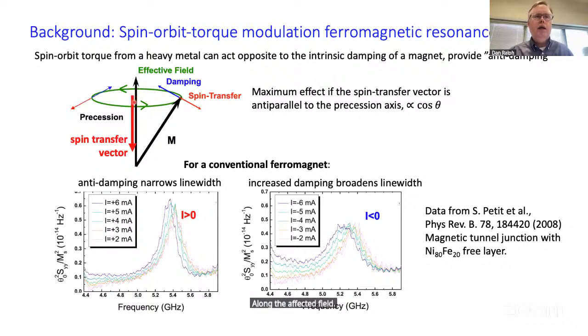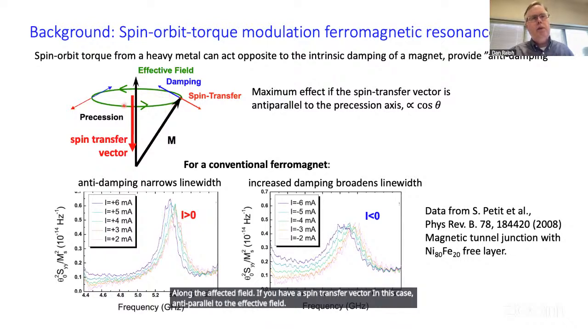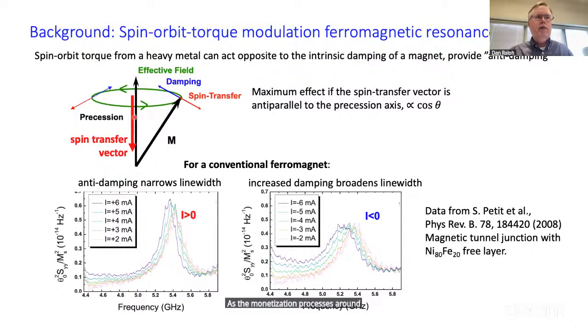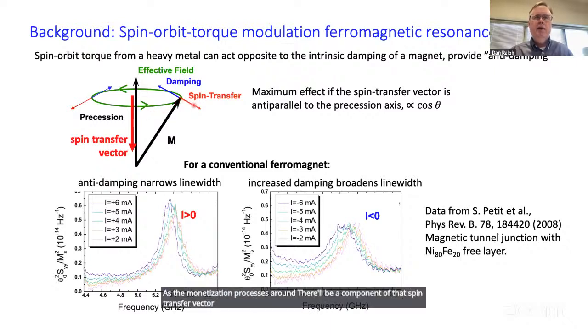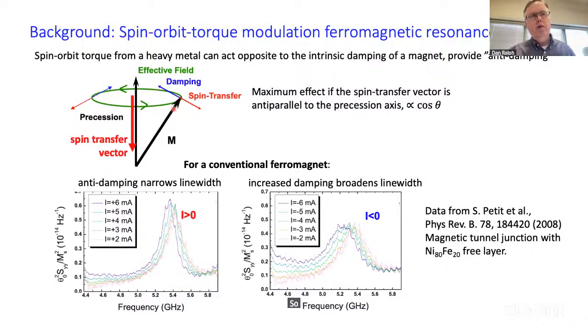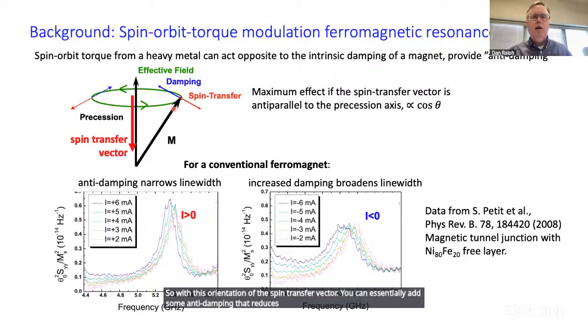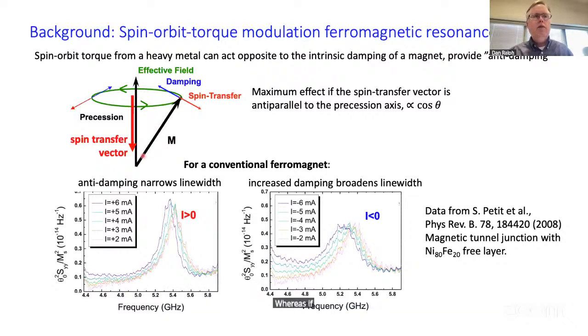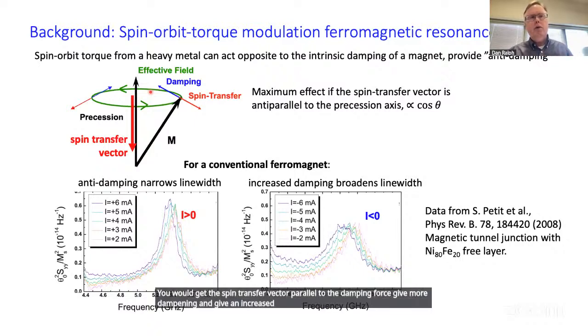If you have a spin transfer vector, in this case, anti-parallel to the effective field, as the magnetization precesses around, there'll be a component of that spin transfer vector that points opposite to the natural damping at every point along the precession axis. So with this orientation of the spin transfer vector, you can essentially add some anti-damping that reduces the natural damping and causes the FMR line width to decrease. Whereas if you reverse the sign of the current, so as to reverse the direction of the spin transfer vector, you would get the spin transfer vector parallel to the damping force, give more damping, and give an increased line width in a ferromagnetic resonance measurement.